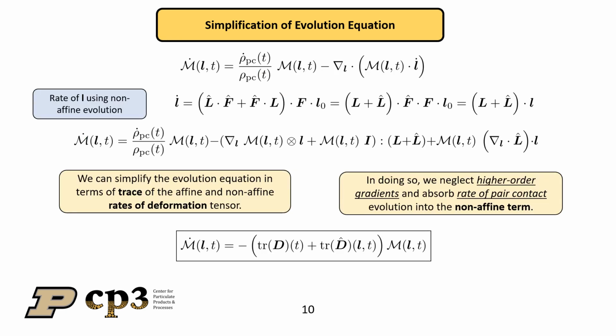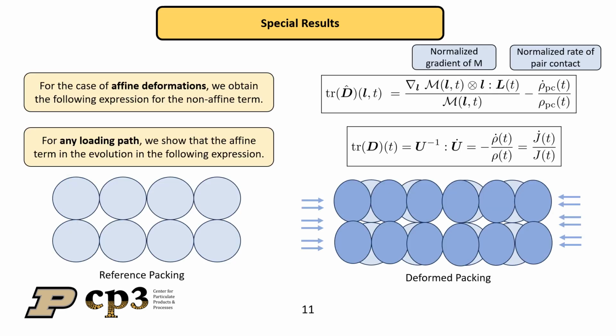We now show how to simplify the evolution equation by assuming the multiplicative decomposition of the branch vector L, which subsequently becomes an additive decomposition of rates, where we have an affine velocity gradient and a non-affine velocity gradient field that depends on the microstructure. We can then subsequently simplify the evolution equation by neglecting higher order gradients and absorb the rate of pair contact evolution to obtain a scalar evolution law that simply depends on the trace of affine and non-affine rates of deformation tensors. We now show some special results for the affine and non-affine terms.